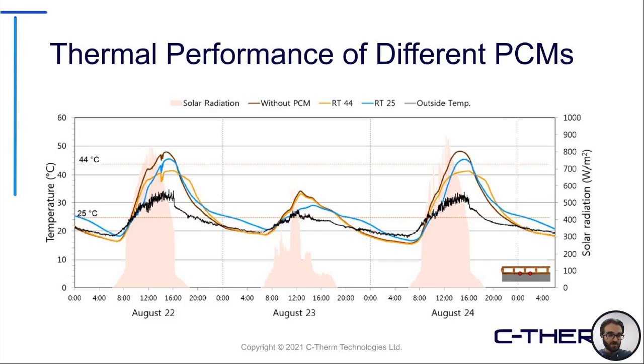So we can see in general here, the overall temperature rise in the sample as a response to that radiation was generally seen to be higher in the samples that contained no PCM, and overall were somewhat lower with the various PCMs added. And again, this is what we would expect to see. The PCM is coming in there as a stability device, aiming to reduce the overall increase that was observed in the wood plastic composite.